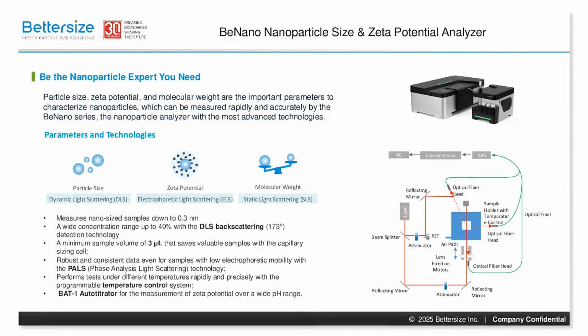For comprehensive zeta potential analysis across a wide pH range, the BAT1 auto-titrator is seamlessly integrated. It also measures the size of nano-sized samples down to an incredible 0.3 nanometers, covering a wide range of particle sizes. Its wide concentration range up to 40% is made possible by its DLS backscattering technology.